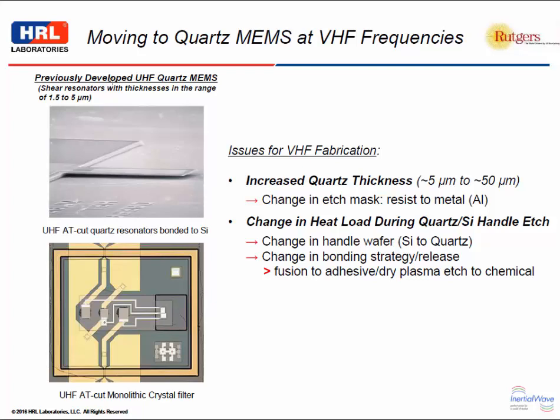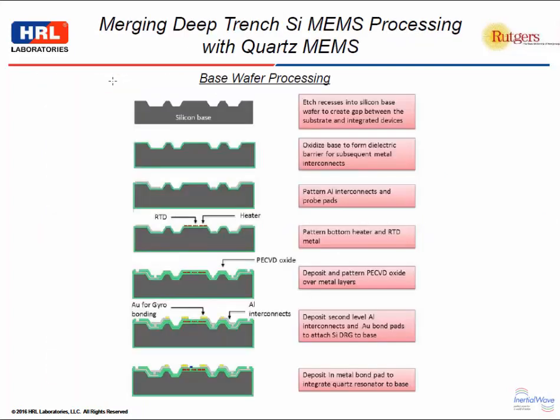So we had to switch from using a quartz silicon fusion bond to bond the active layer to the handle wafer while we were processing it, to an adhesive bond. And we went from a dry plasma etch of the handle wafer to a chemical etch to remove the adhesive. So that was a fairly substantial change in the process, and I'll show you where that comes in a few minutes. So the process, and if you're not a process person, forgive me, but the real key here is in all the little details of the processing. So let me step you through the processing.